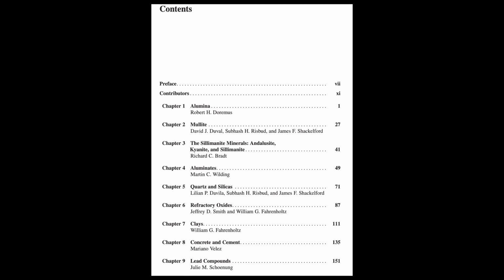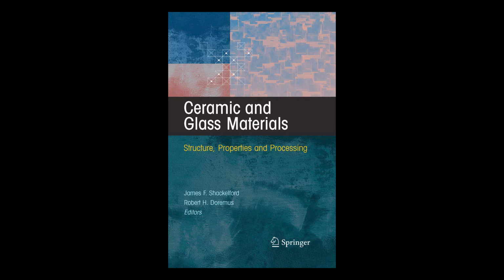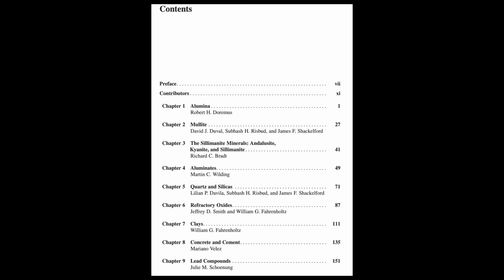Okay. And what happens if you take these natural minerals and just heat them up in normal air? They all decompose. They transform into 3:2 mullite and silica. Ah, they turn into mullite. They do. Interestingly, the 2:1 mullite doesn't seem to form directly from this decomposition. And the type of silica you get can vary depending on which mineral you start with. And do they all decompose at the same temperature? No, that varies too. Kyanite starts breaking down lowest, maybe around 1150 C, and andalusite is next, about 1250 C. Sillimanite holds out the longest, starting closer to 1400 C. So sillimanite is the most heat-resistant of the three. Before decomposition, yes. And the temperature range over which they fully convert also varies. These temperatures can even shift a bit depending on where the mineral came from geologically and what impurities it has.